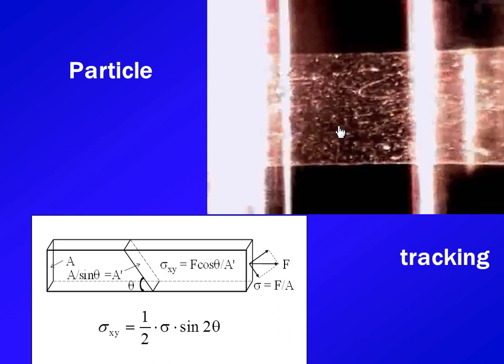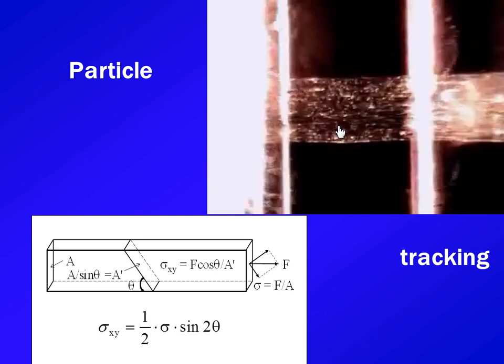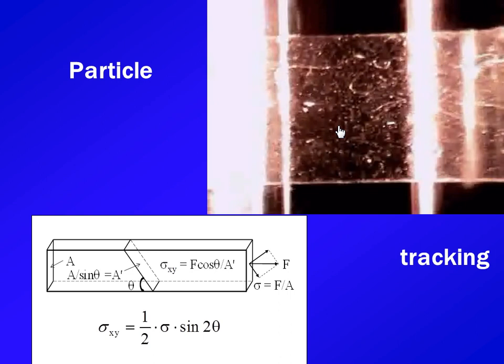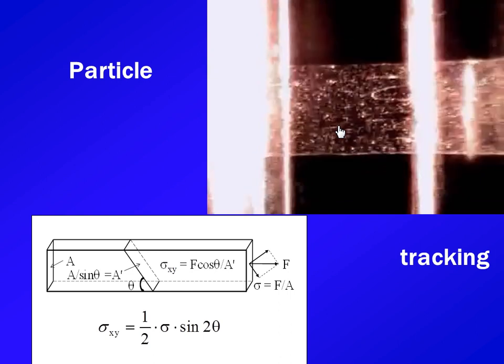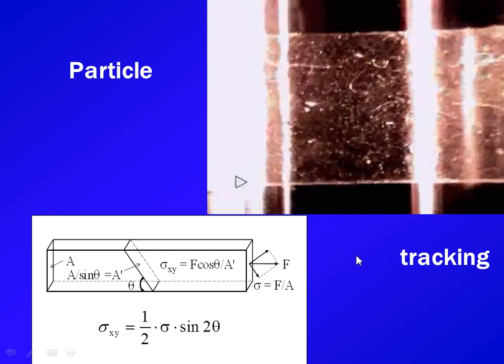And the system knows the chain, and it's very intuitive. The chain knows to slide this way. Perpendicular along the stretching direction is much more difficult than at an angle, which is by shear. So the shear yielding becomes the favored mode that leads to failure or initializes the non-uniform deformation.